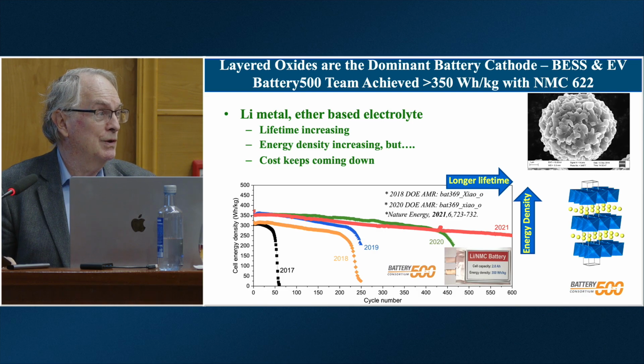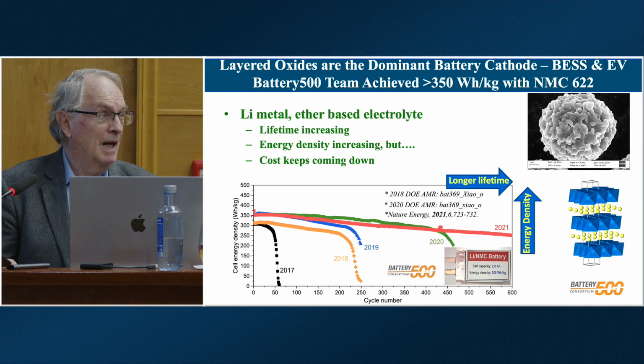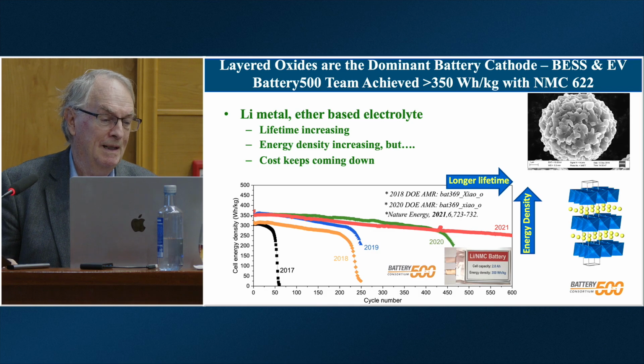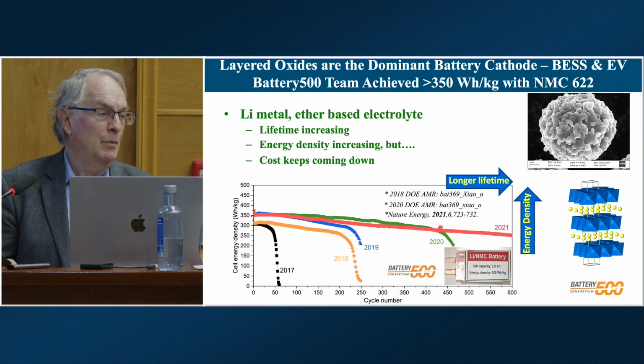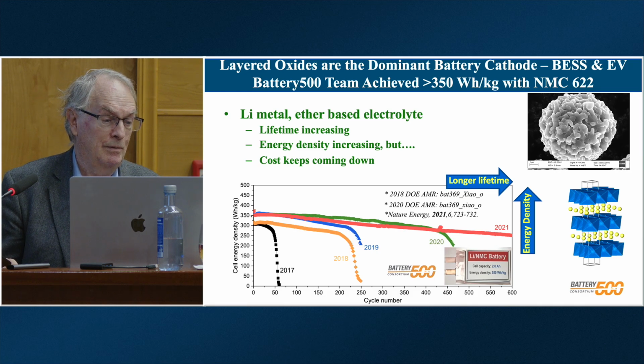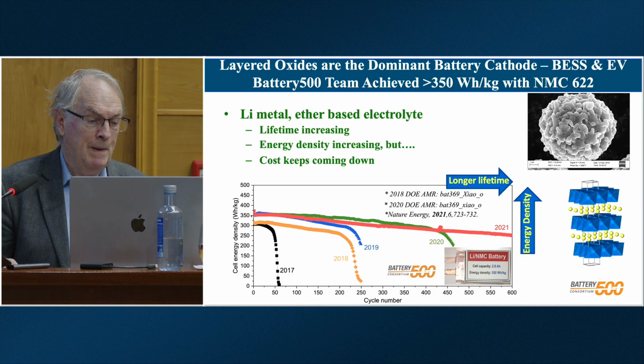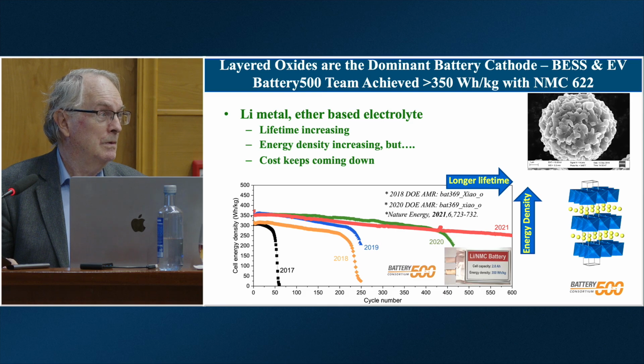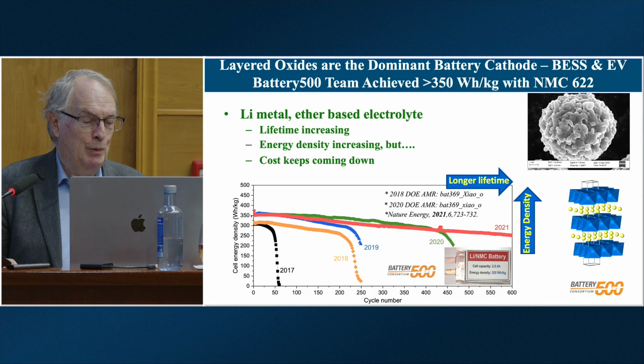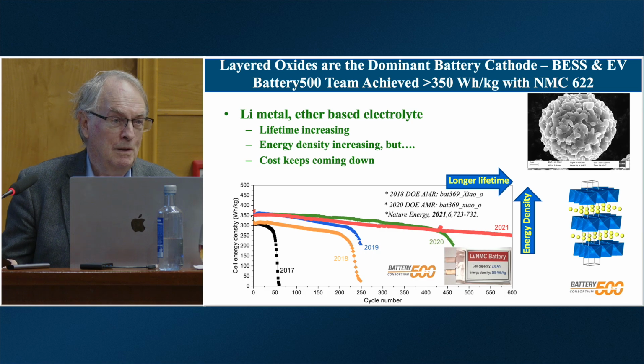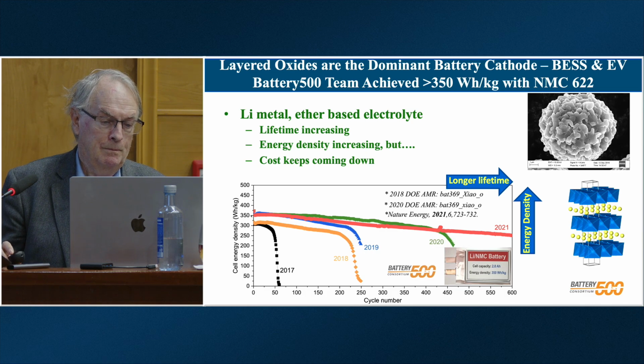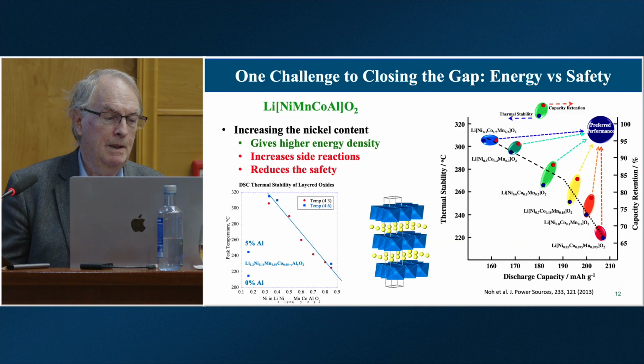And you can see in our first year in 2017, we could cycle these batteries about 50 times before they lost all the capacity, in other words, before they died. A year later, we'd got up well over 200. The year after that, we raised the energy density from 300 to 350, and today we're about 600 cycles at 350. So we've shown we can do it, and right now we're pushing towards the target of 400 or 500 watt-hours per kilogram.